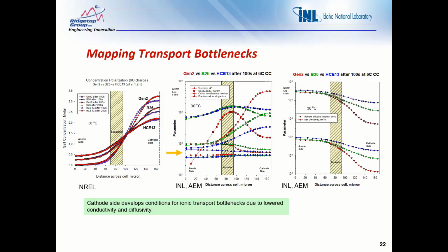So compare that to the other 2 electrolytes, B26 and HCE13, which are the green and blue squares. They remain relatively high across the cell. So there's not a lot of change in properties as we go across. There are some changes, but not nearly as dramatic as what we saw with the Gen 2. So it's going to be more well-behaved. You're going to be able to sustain the charge conditions longer with these types of electrolytes than you could with the baseline. And on the right-hand side, we have some diffusivity shown for these 3 electrolytes.